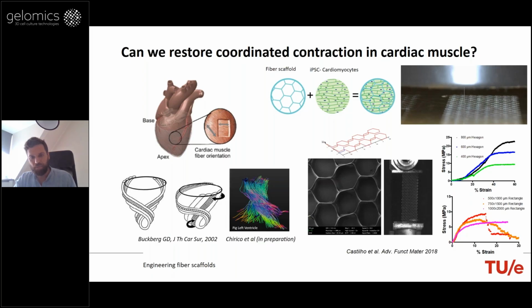What you see here from the bottom right side of the PowerPoint is a comparison of printed hexagons with different pore sizes under uniaxial tensile loading with the same PCL printed, but now instead of in a hexagonal geometry, printed in a rectangular geometry. And what you can appreciate is that the rectangular shaped constructs, above 5%, and I don't know if you can see my pointer or arrow, start to undergo plastic deformation, while the hexagons went up to 30 to 40% within the elastic regime. So clearly, by just playing with the design, we could adjust the elastic properties of our constructs.